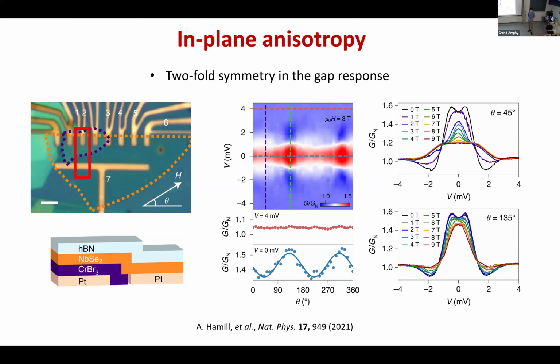How do you get a peak in the tunneling contact? It's a low Z measurement, not strictly tunneling. It's an array of couplings. This layer is not insulating; it's a very thin tunnel barrier. So the Z parameter in the BTK model is small, close to 1. These things sometimes appear.